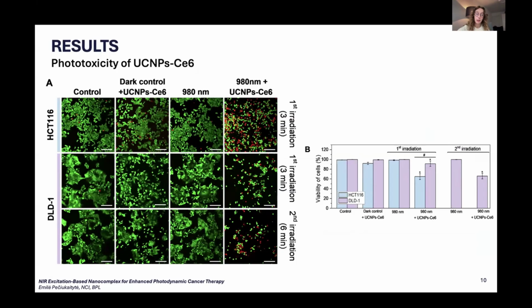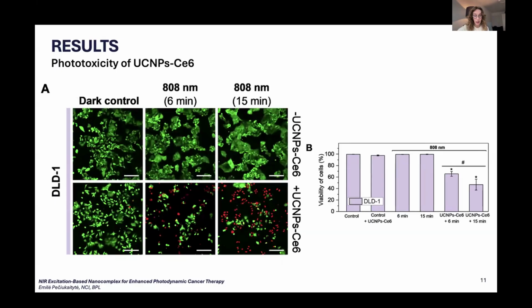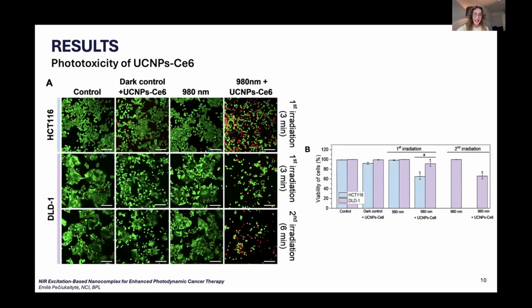Cancer cells were incubated with the nanocomplex for 24 hours and irradiated with a 980 nanometer laser. After 3 minutes of irradiation, HCT cell viability decreased to 65%, while DLD1 cells were more resistant, showing 91% viability. So to further investigate dose dependence, an additional 3-minute irradiation was applied to DLD1 cells, and the viability then decreased further to 66%, accompanied by clear morphological signs of apoptosis or necrosis, such as cell rounding and loss of adhesion.